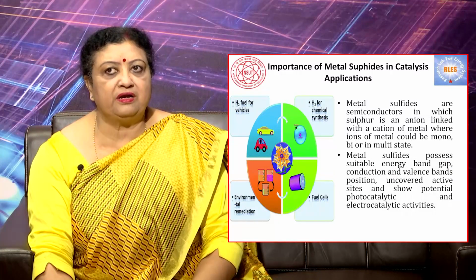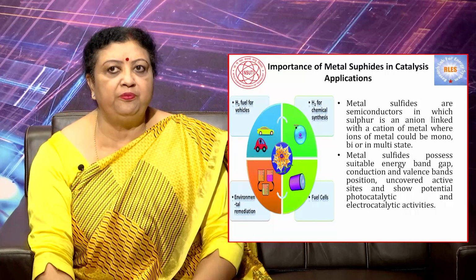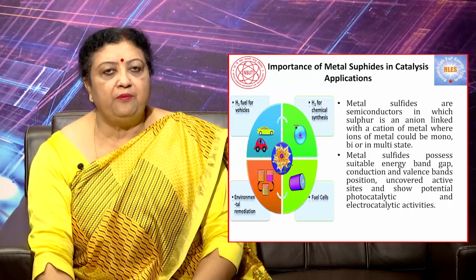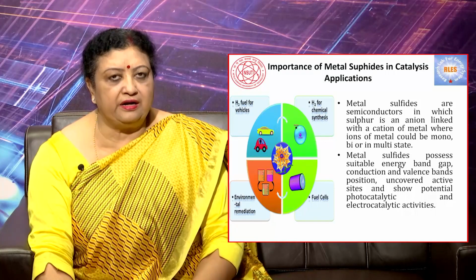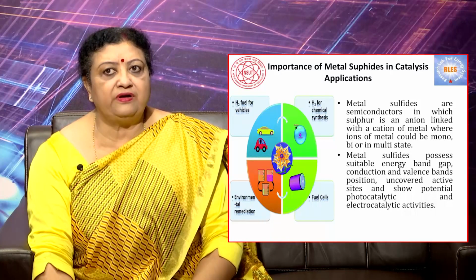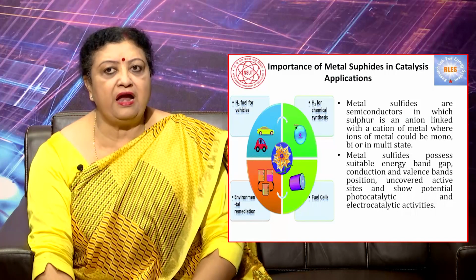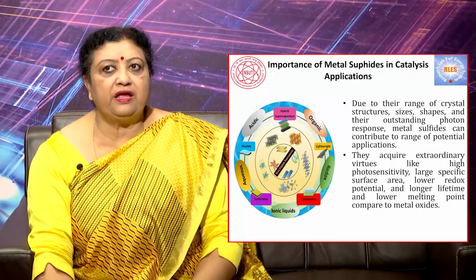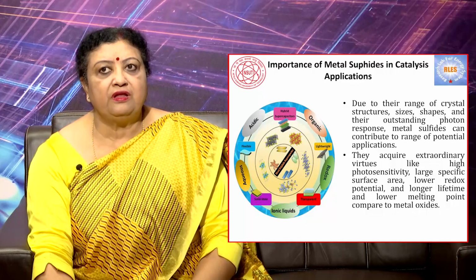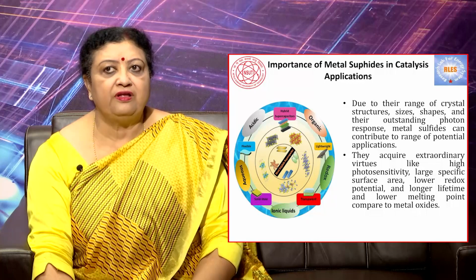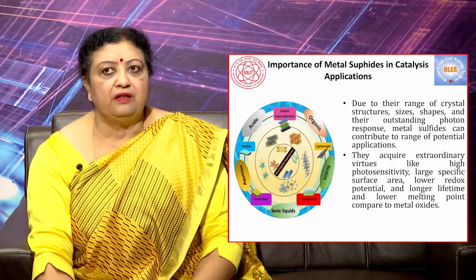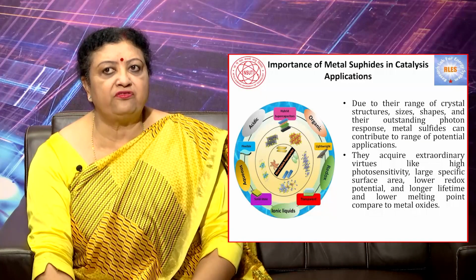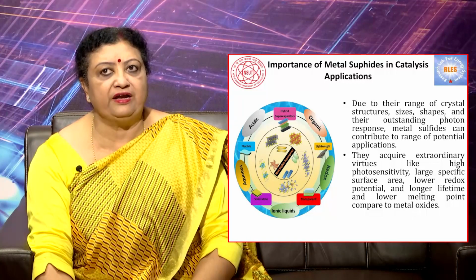Metal sulphides are semiconductors in which sulfur is an anion linked with a cation of metal, where the metal ions could be mono, bi or multi-valent. Metal sulphides possess suitable energy bands, conduction and valence band positions, uncovered active sites, and show potential photocatalytic and electrocatalytic activities. Due to their range of crystal structures, sizes, shapes, and outstanding photon response, metal sulphides can contribute to a range of potential applications. They acquire extraordinary virtues like high photosensitivity, large specific surface area, lower redox potential, longer lifetime and lower melting point compared to metal oxides.